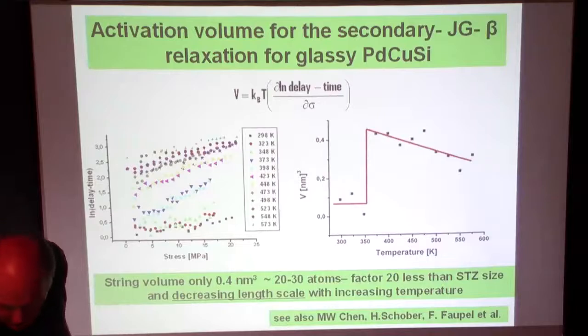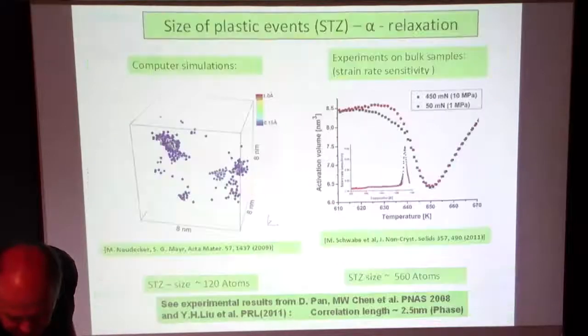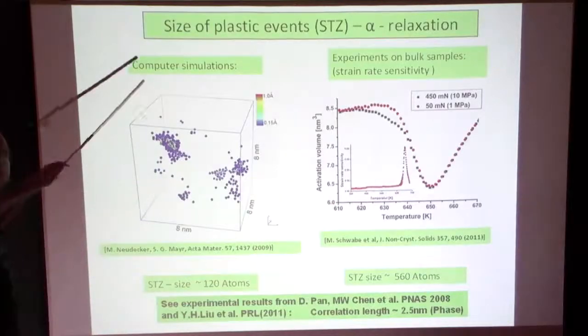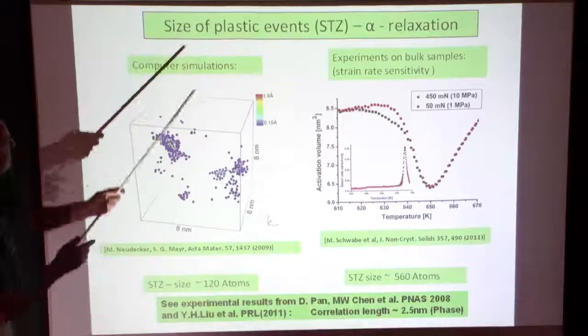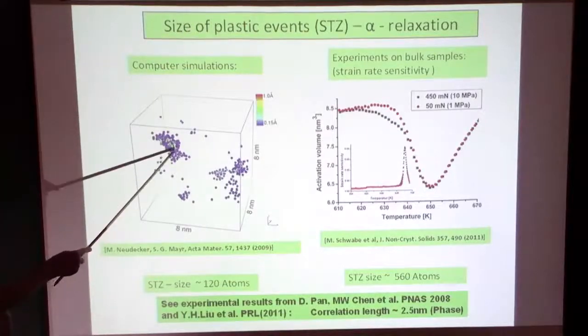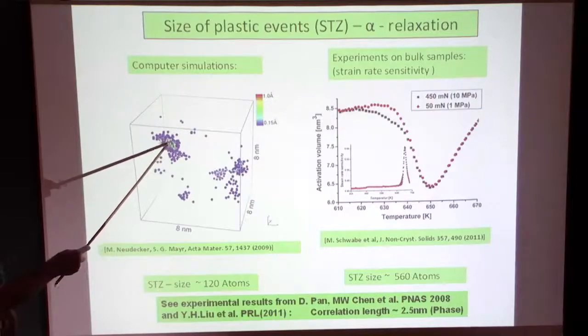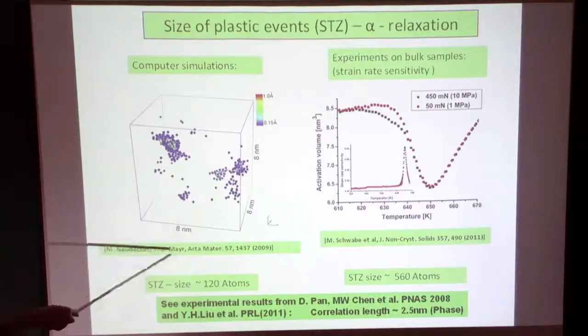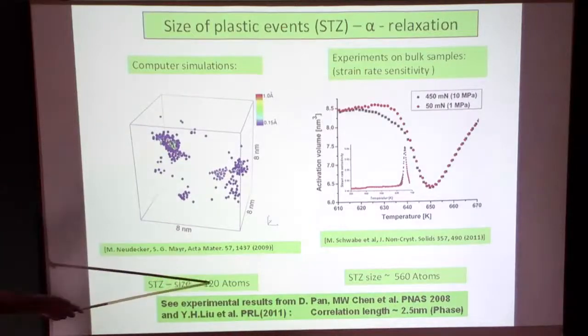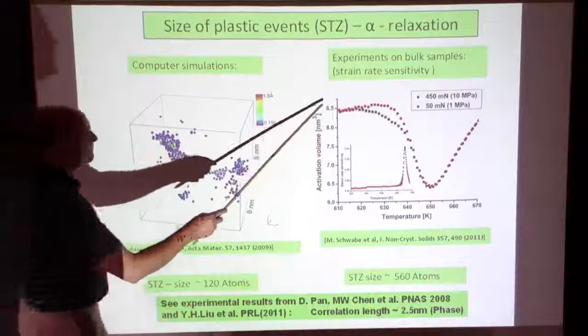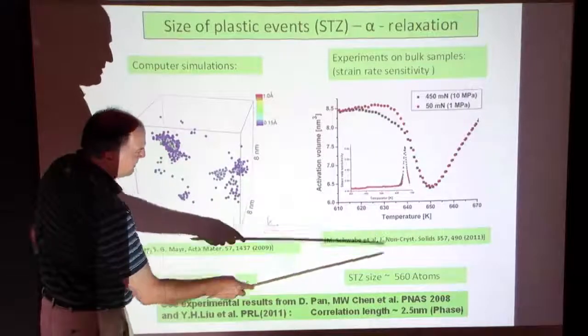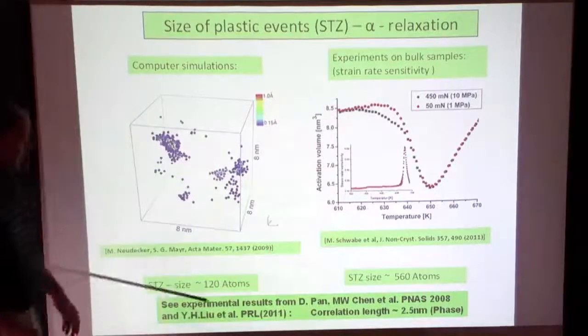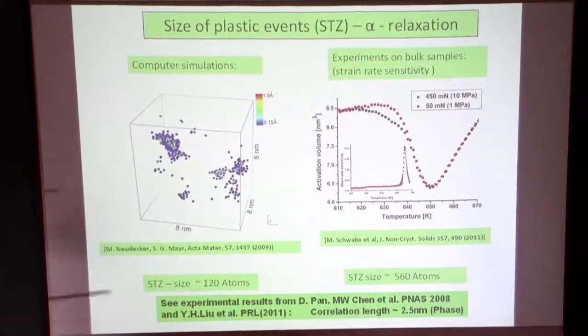So that is the volume we talk about in these strings, a factor of 20 smaller than what we call the plastic events. In the simulations at least, you have a very plastic core and some kind of elastic shell surrounding that. That is Stefan Mayr's work, and you get 120 atoms. If you do real mechanical measurements, the size is much bigger, but obviously you include a much larger size of the stress field, in these apparent volume measurements.